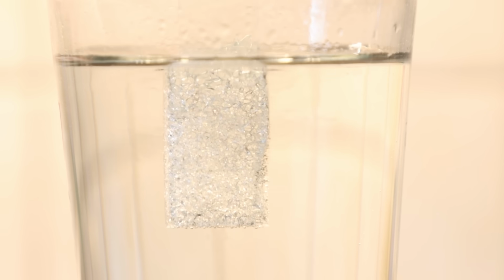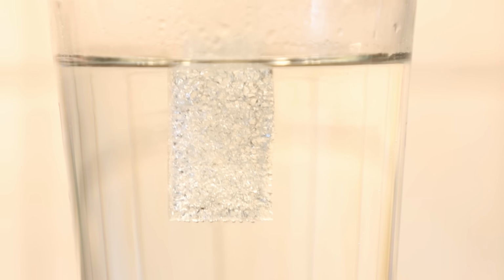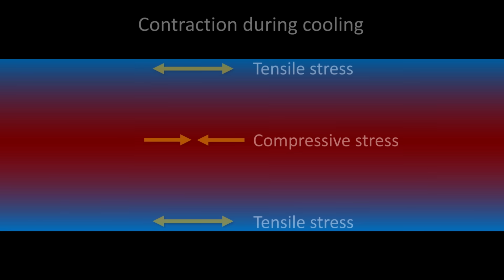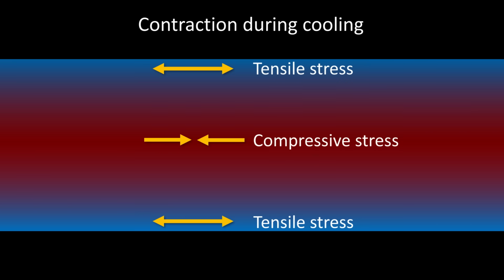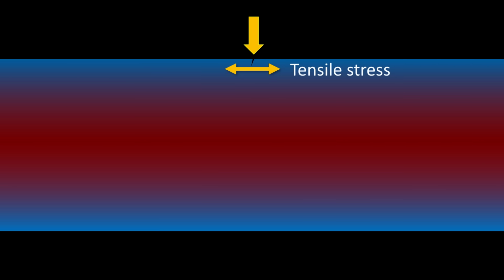So in the experiments just shown, we cool down a sample rapidly from the outside. This leads to a temperature gradient in the glass, especially since it's not a very good conductor of heat. And given that glass contracts when cooled down, this gradient leads to tensile stress in the outer layer and compressive stress in the core of the object. And if the tensile stress that is introduced is higher than the material can handle mechanically, cracks can easily form from small surface defects, which then propagate inwards.